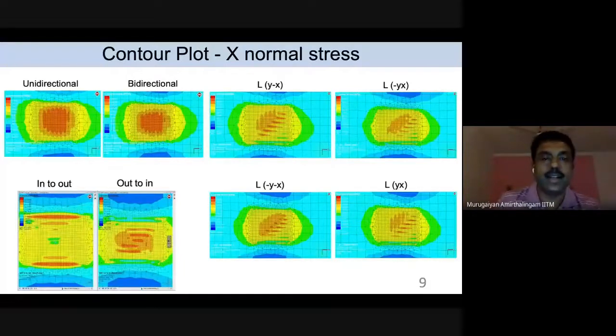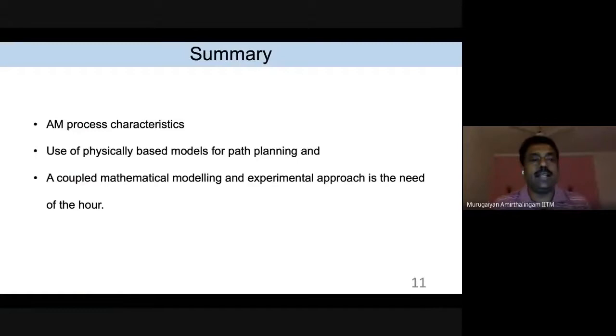So these are some of the scans. We looked at the AM process characteristics and how we have to understand the basics. Once we understand the basics, we can construct physically based models for path planning, which can be used very effectively to reduce the experimental efforts. So that using these simulations, we can identify the best path we can take, so that we can minimize the residual stress, distortion and heat accumulation, so that the layer can be generated without much residual stress and with minimal damage to the microstructure.